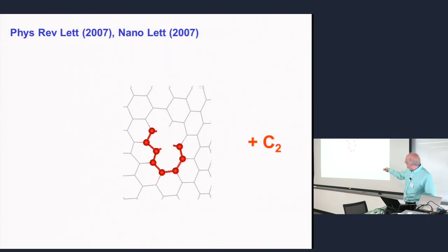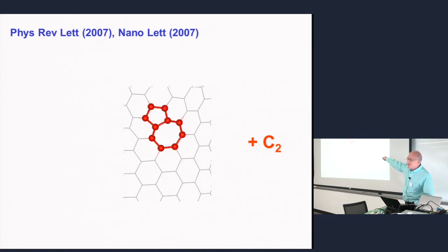If I remove these two atoms, they go into gas phase, being knocked away. Now you have dangling bonds here, and these dangling bonds find each other immediately. Now if they connect, and this one connects, you fully recover the same structure. So basically, it jumps one step forward. It just shifted, but you did not create any new degree of disorder. That's why the energy cost is lower than any other place. Because if you remove it from somewhere else, you increase disorder in the material. You either have extra dangling bonds, or you have some strain configuration which did not exist before you removed carbon. But in this case, nothing like this. It's just translated. And actually, it makes perfect sense if you think about dislocation theory in crystals. This process is called climb.